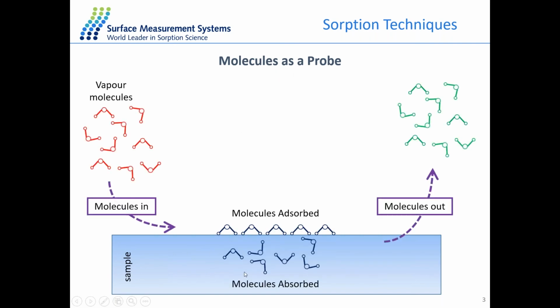So for the sorption technique, with the characterization of the solid material, we can either use energy or heat as a probe. And in case of the sorption technique, we will use a molecule as a probe to interact with the solid sample in the bottom here. So by studying the kinetics of this sorption and desorption, we can then determine some of the properties of this solid material at certain conditions, at a combination of temperature and relative humidity.